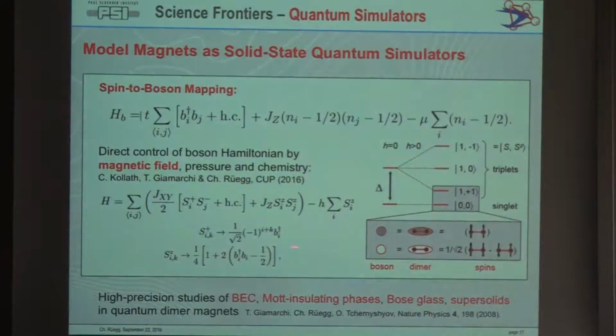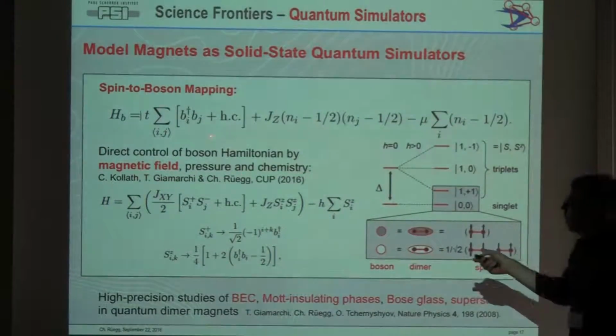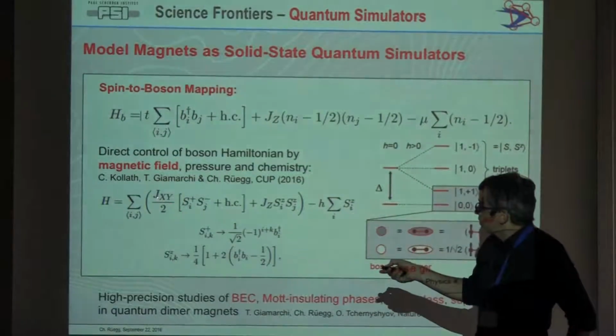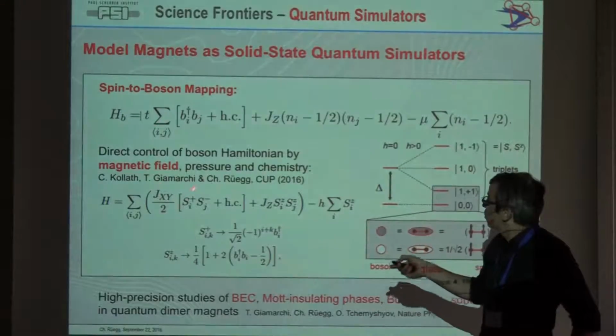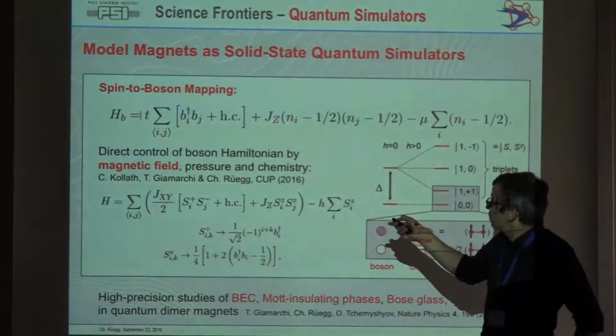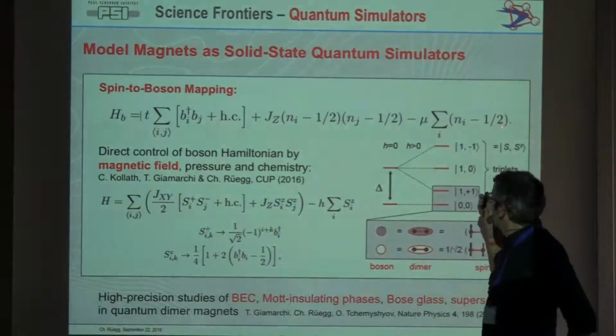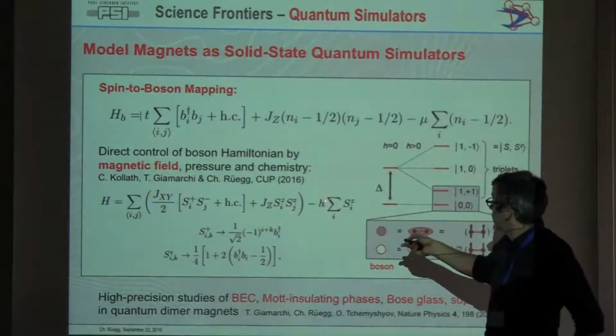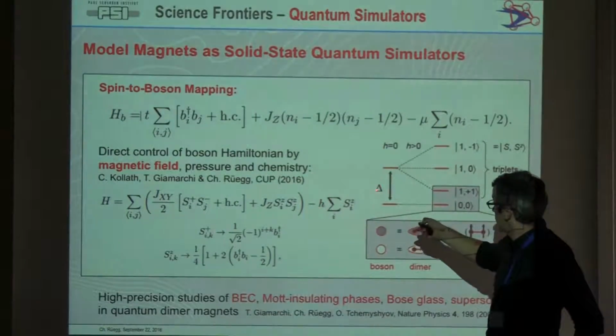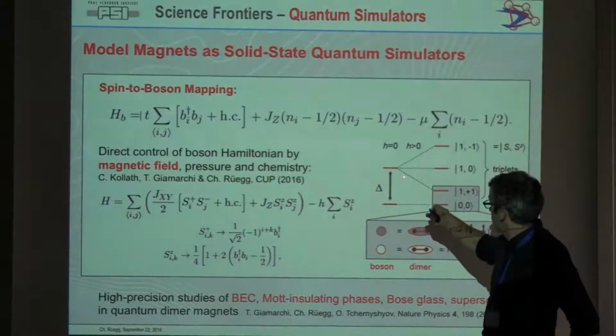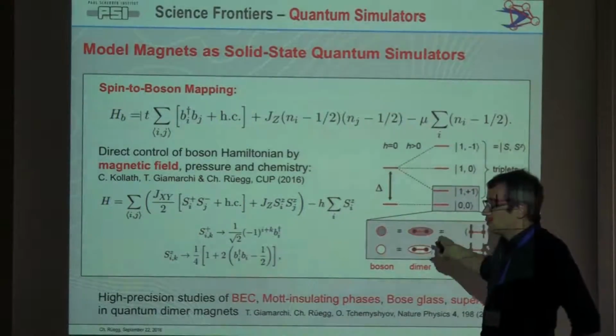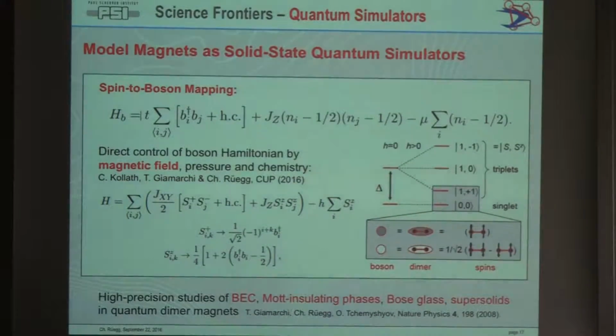If you go to an effective quasi-particle picture, that would be the one above. You have a hopping term based on exchange parameters, in the x, y direction. There's an interaction term, which is the Z component. And there is a chemical potential, which essentially is driven by the magnetic field. So if there's a gap in the chemical potential, you close it down. In a very similar way, we have seen this earlier in this session. So this is now a powerful analogy.